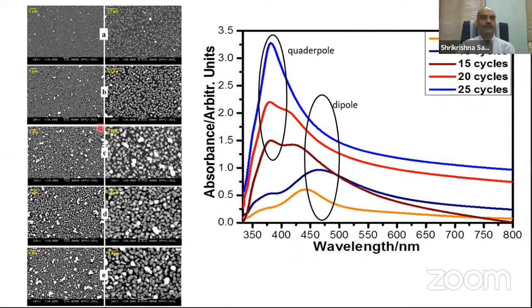That is one thing. This is one typical result. I'm not going to discuss our results in detail because they are already published, so if you are interested, you can look at them. But what we can see is that if I change the cycles of the SILAR, the size of the nanoparticles changes and their separation decreases. They lose the spherical symmetry and get a kind of nanorod shape, because you can see that these two nanoparticles are merged with each other. And if they merge with each other, in the surface plasmon resonance you get two kinds of peaks. The dipole peak we get whenever they are only spherical nanoparticles.